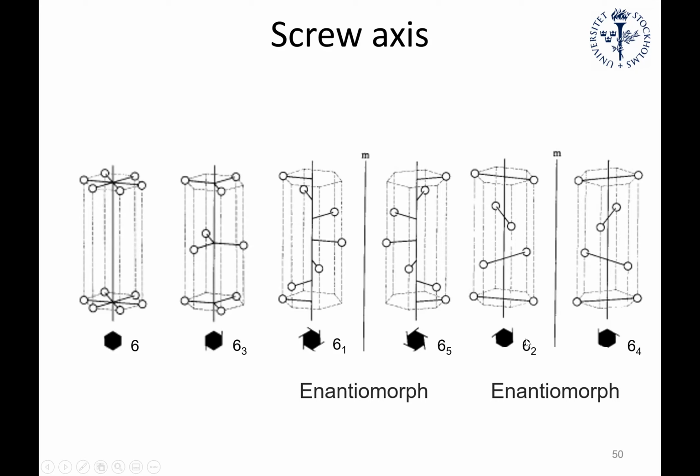Okay, let's talk about 6-2 now. So again, the 2 indicates you have a twofold rotational symmetry as well. So there is twofold symmetry, but now it's still a 6-fold. So we rotate it 60 degrees, and now we translate it 1/3 of the unit cell up. So that's like 2 divided by 6 gives you 1/3. So that tells you how much you can translate.